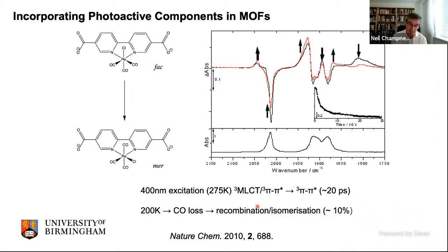Now, if you study this same photoexcitation process at lower temperatures, so 200 Kelvin, you can actually see CO bands growing in. So this is actually free CO. And this then recombines with the rhenium complex because it can't escape from the framework because the framework is not porous. And it recombines, and this can result in isomerization of the rhenium center from the FAC isomer to the Mer isomer, depending on where the CO recombines. And in the case of this rhenium complex, this happens in approximately 10% of the rhenium centers. So we get 10% isomerization.